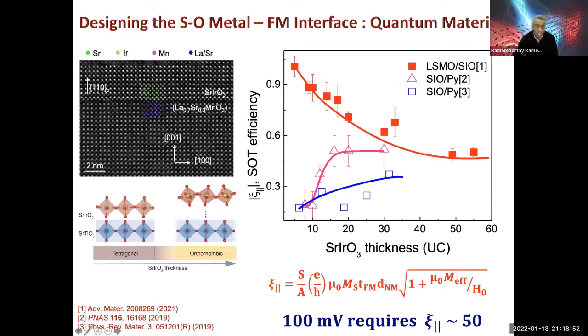So what you see here is lanthanum strontium manganite, which is an oxide ferromagnet. And on the other side, instead of platinum as the spin orbit metal, we use strontium iridate. Now, strontium iridate 113 behaves very much like a topological insulator. It has some very interesting electronic structure. It has band crossings in its electronic structure. So it has topological kind of behavior. It has iridium, so you have very large spin orbit coupling.